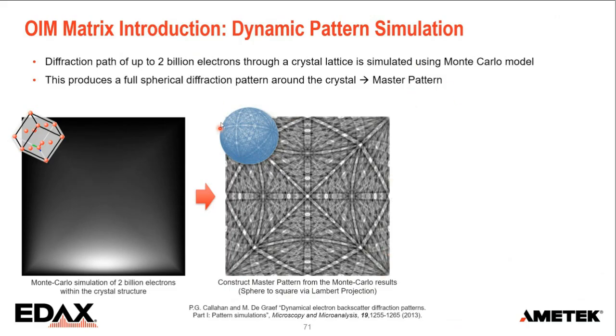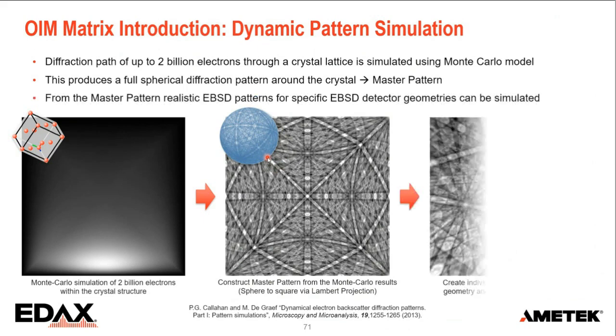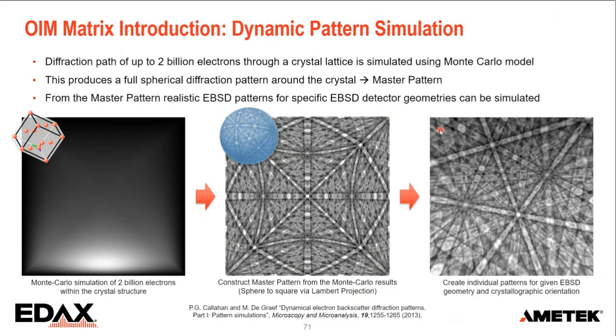So once we have calculated all the possible diffraction directions that we're getting, we get all these patterns. We can extract a pattern from a very specific orientation. And this orientation can be made to match your EBSD camera and microscope geometry.